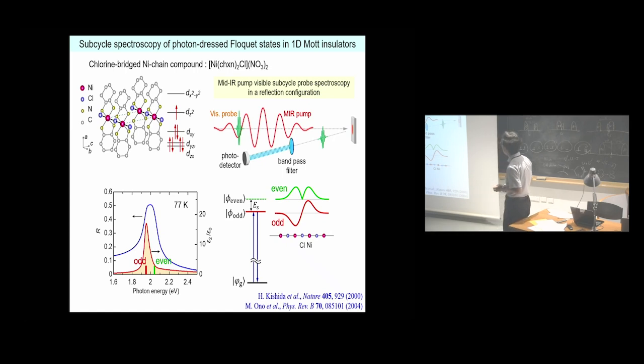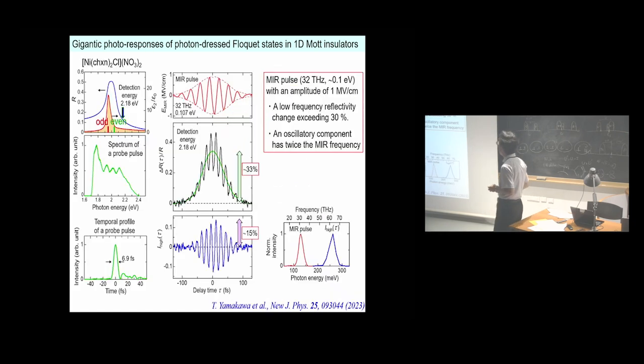We performed the mid-IR pump visible subcycle probe spectroscopy in a reflection configuration. This is the temporal profile of a probe pulse, and this is its spectrum, which covers the wide energy range around the odd parity state and the even parity state. By a mid-infrared electric field, a large reflectivity change with rapid oscillations is observed near the absorption peak. A low frequency reflectivity change shown by the green line exceeds 30%, and the oscillatory component extracted here has twice the mid-IR frequency, like this.